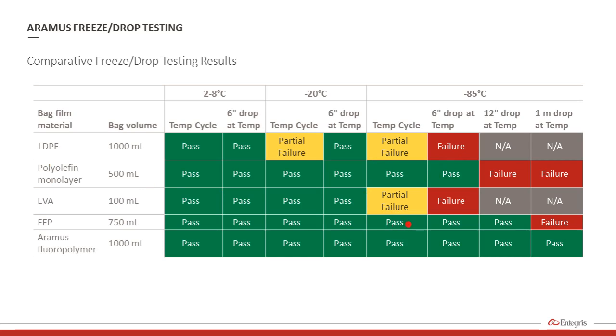Next, the FEP bag passed the temperature cycle, it passed a 6-inch and 12-inch drop, but failed at the 1-meter drop. And finally, the Aramis fluoropolymer passed all the temperature exposures, even down to minus 85, and it passed a 6-inch drop, the 12-inch drop, and it was the only one to pass a 1-meter drop at a minus 85 degree temperature range. Again, this assures that the product being contained in the bag has less risk due to droppage of the bag.